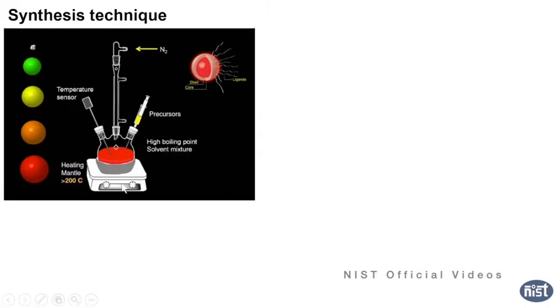Like here you see, it's just a simple setup: a magnetic stirrer, and you have a temperature controller here. You can set a temperature, and it's a 3-neck flask. You have a solution, and from one neck you can inject the precursor, for example for cadmium selenide, you can add cadmium, selenium, and other precursors, whatever you like.